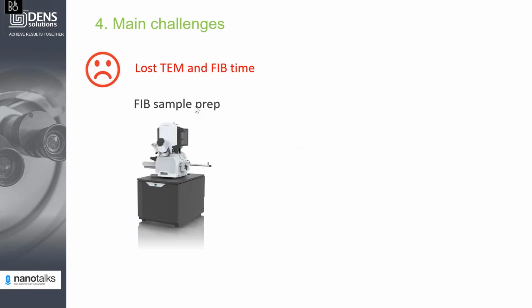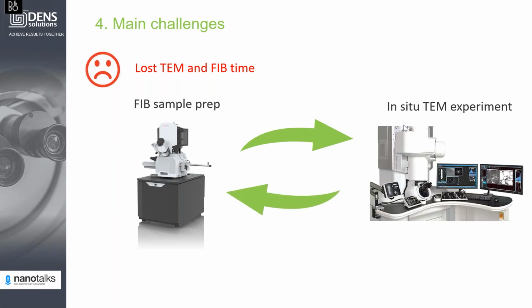So the issue with all those challenges is that if the sample preparation is not done properly, you will lose TEM time and FIB time. So how does it work? You prepare your sample. Afterwards, you take it to the TEM, you assemble the system, and you try to measure. If the sample is not prepared properly, you will not see the effect you're looking for.